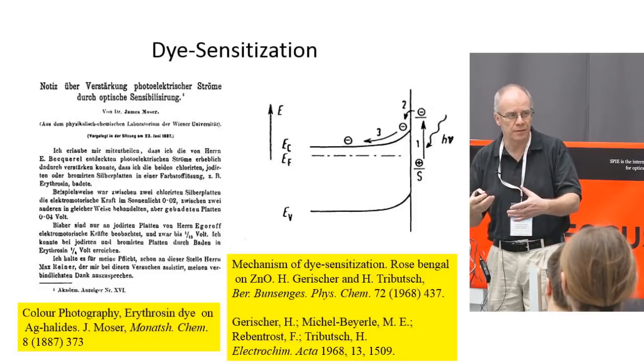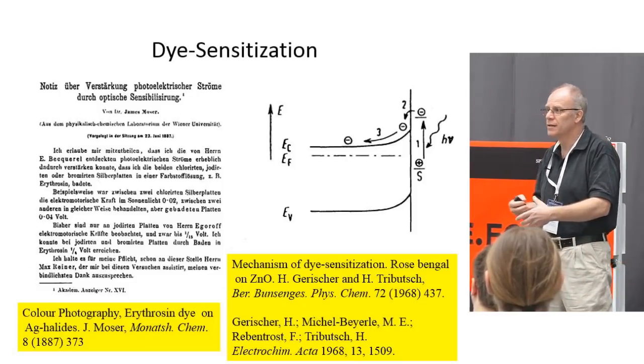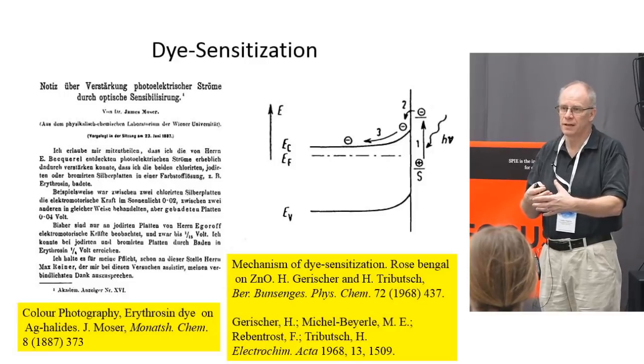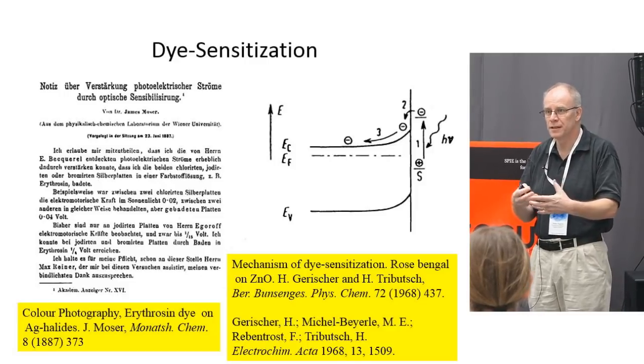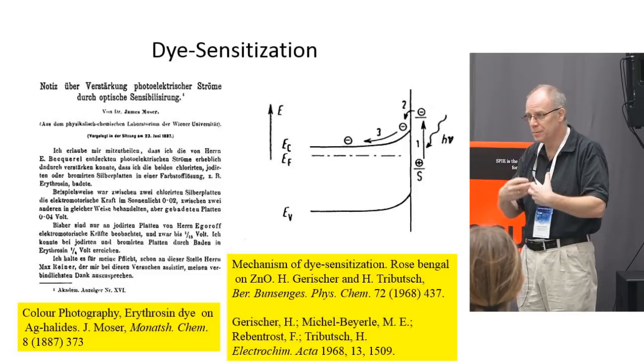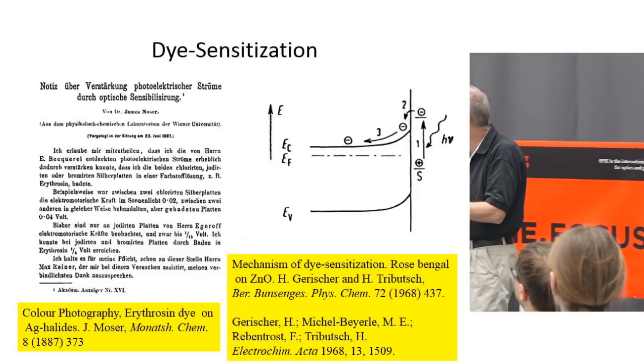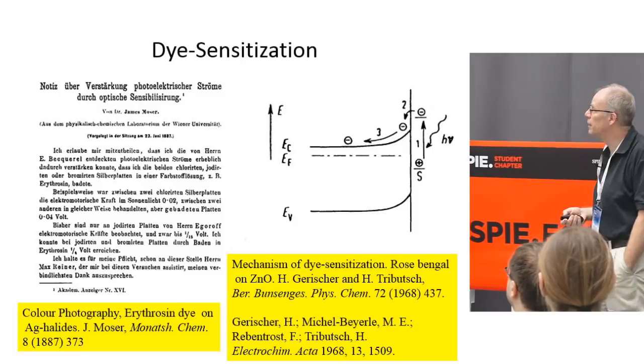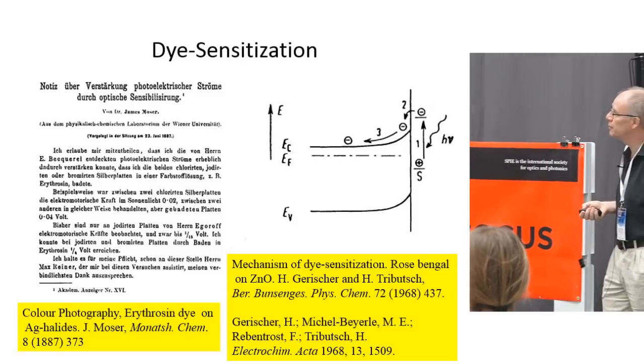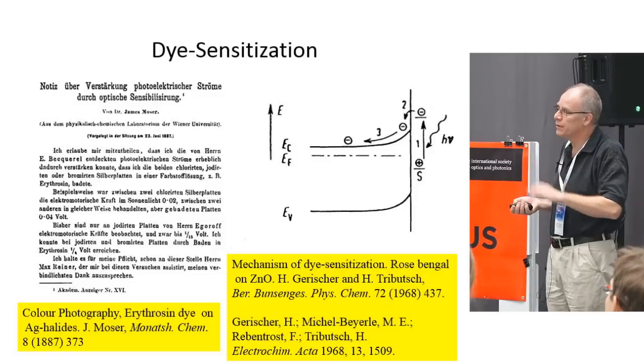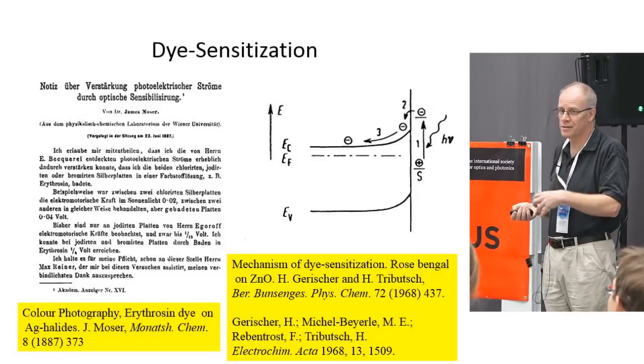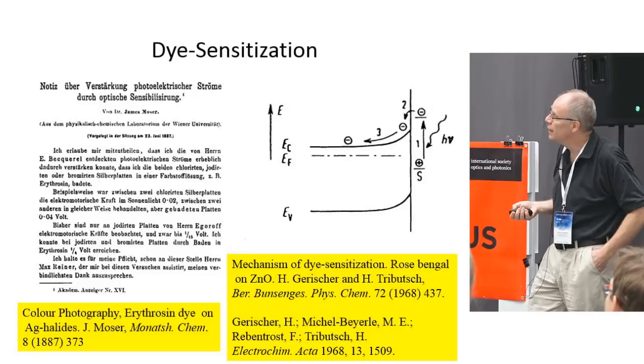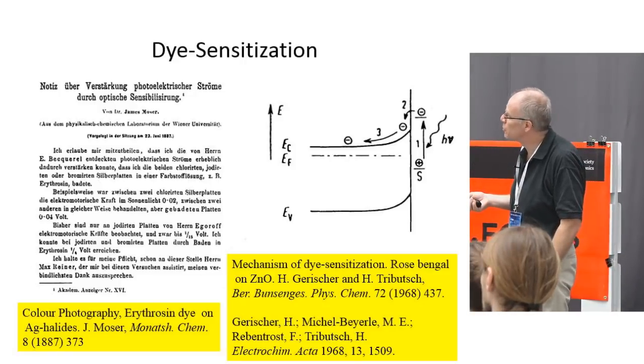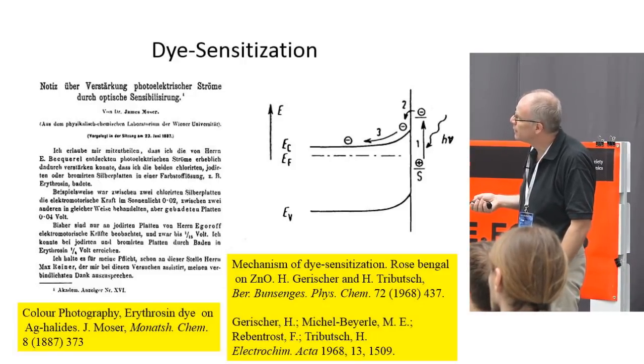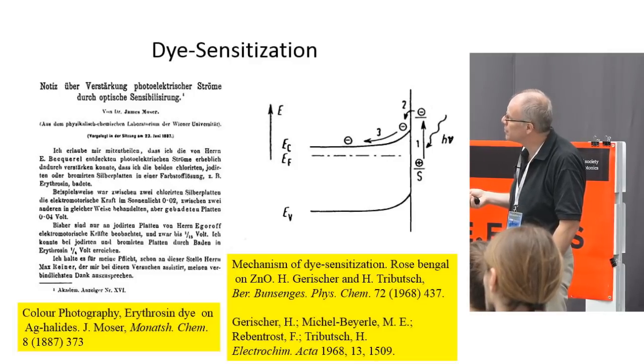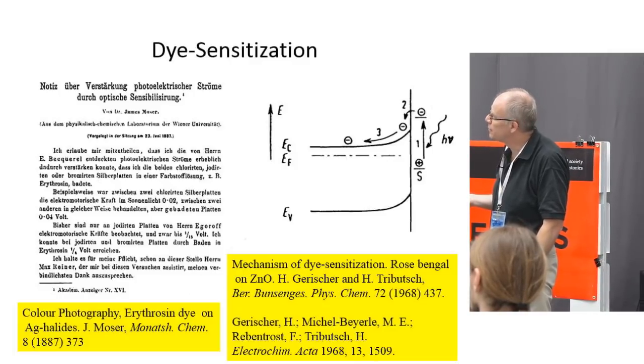And when you illuminate that, you can get an electron in there, which you can then develop and get a picture. To make that from black and white to colored, you need some kind of dye molecule to absorb light and expose it to make it color photography. So people started to experiment with using dye on silver halide. So today we would say that it's a dye-sensitized semiconductor. And the first one is James Moser in Vienna, 1887, saying that he used a naturally occurring dye on a silver halide.